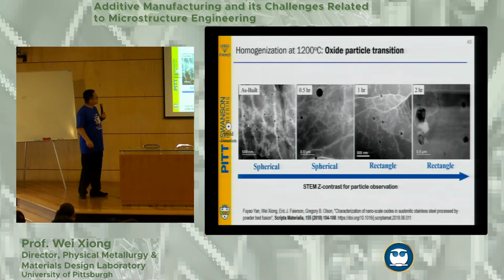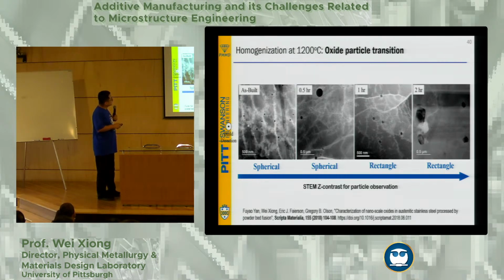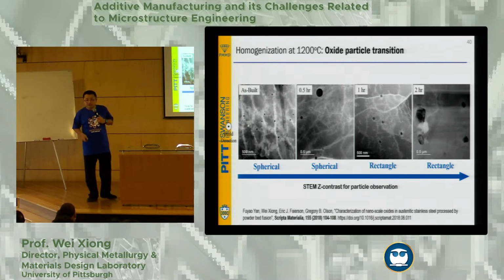After 30 minutes we find some growth, and similarly at 1 hour and 2 hours. And if you look at the shape, it's also changing - starting from between half an hour and 1 hour, it becomes spherical, then rectangular shape.